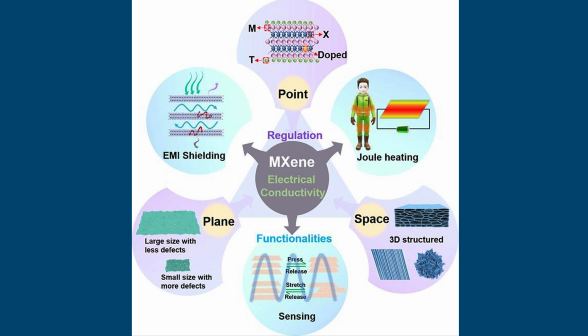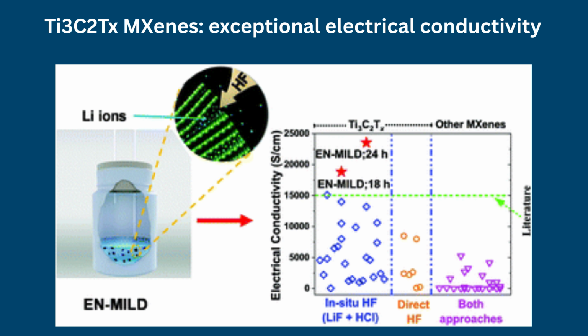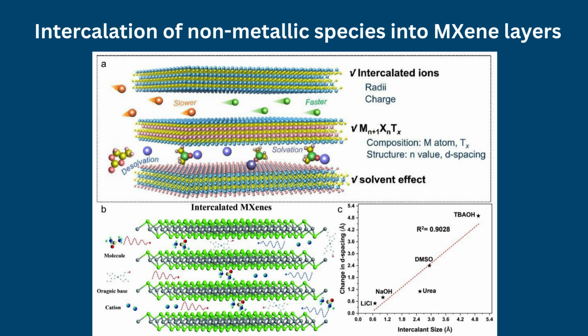One of the most remarkable features of MXenes is their high electrical conductivity. Ti3C2Tx can exhibit conductivity values exceeding 10,000 Siemens per centimeter, making MXenes among the most conductive solution-processable 2D materials. Their conductivity strongly depends on transition metal composition, surface terminations, and interlayer spacing. Intercalation of ions or organic molecules can increase conductivity by facilitating charge transport between layers. Surface modifications through thermal or alkaline treatment can also significantly improve conductivity by altering functional groups and removing trapped species.